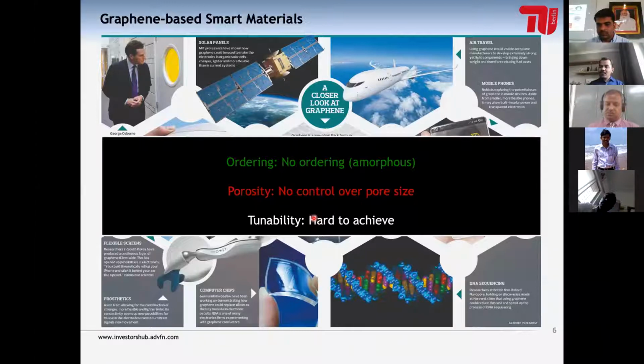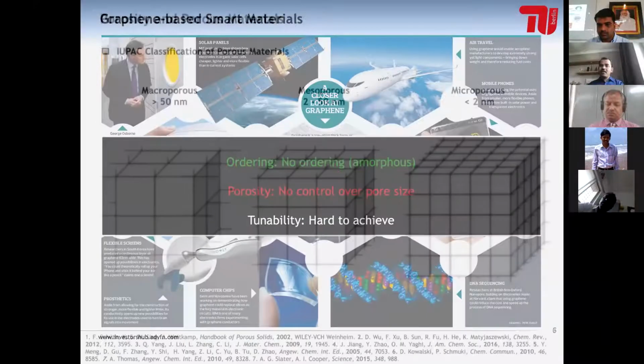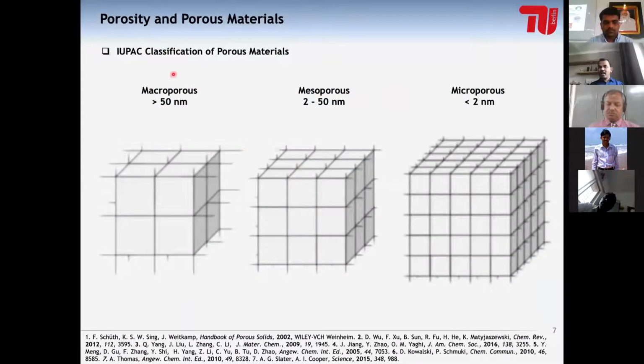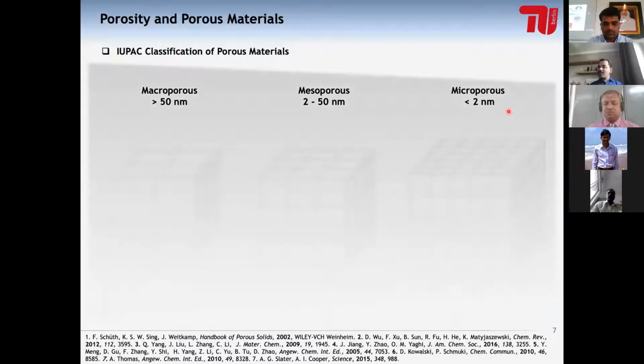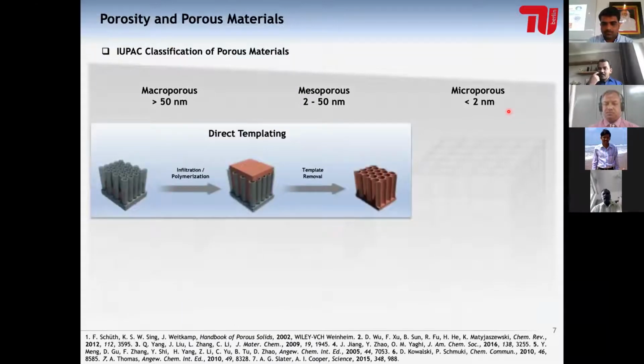So when it comes to porosity, as all of us know, according to the IUPAC nomenclature, materials can be classified into three different parts: macroporous, mesoporous, and microporous, according to what pore size these materials have. And if we look into the literature, we generally see that there are a couple of methods which have given reproducible results, that is direct templating. In this case, you have a template on which you can infiltrate and polymerize some polymeric material, make the carbon out of it or make a polymer out of it, and remove the template to get the material with precise pore size and